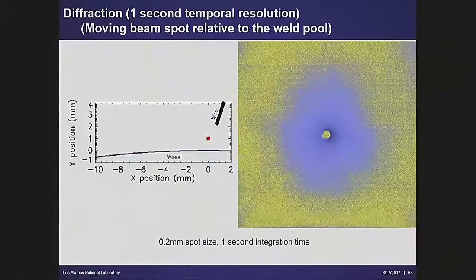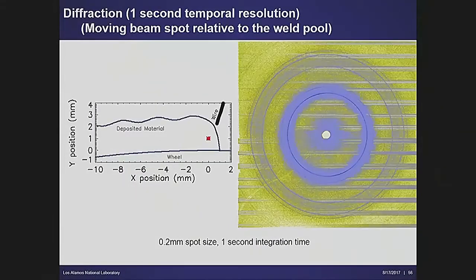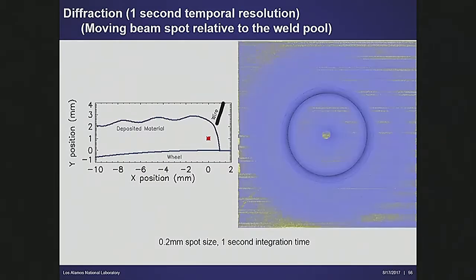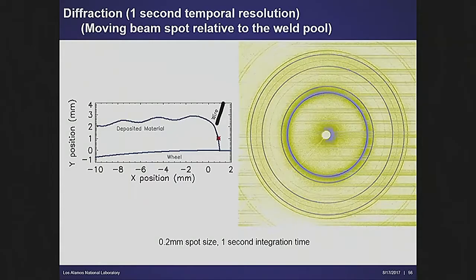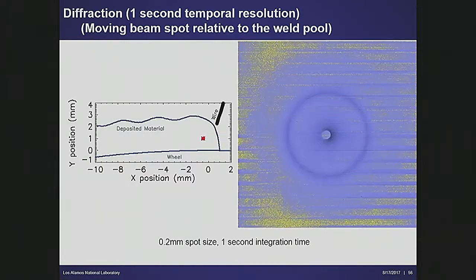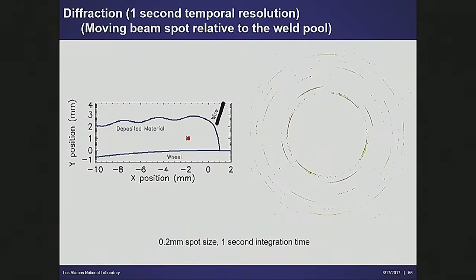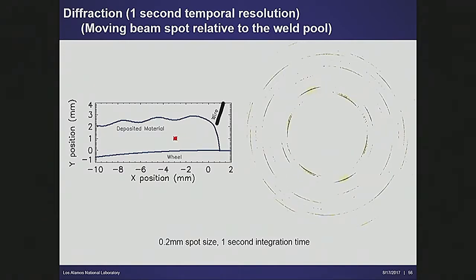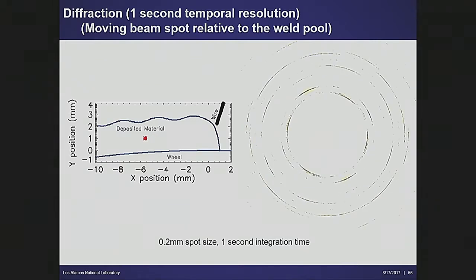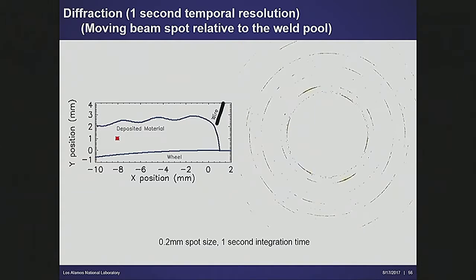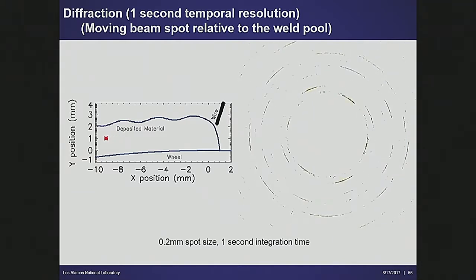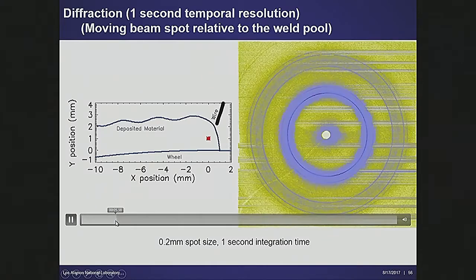So we turn it on, the weld starts, the diffraction spot is here. You can see a series of rings, if you remember from your diffraction at APS. We dragged the spot in front of, back through the weld pool, and then back, and now it's drifting back here. I'll run it again, 0.2 millimeter spot size, 1 second integration time. Remember, you're getting diffraction data out of it.